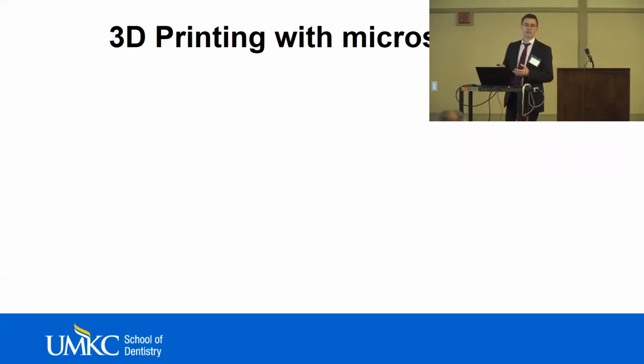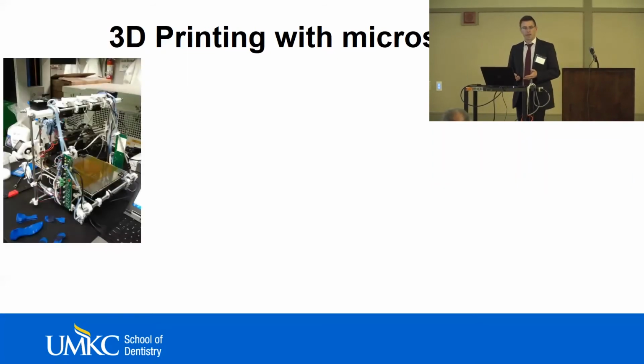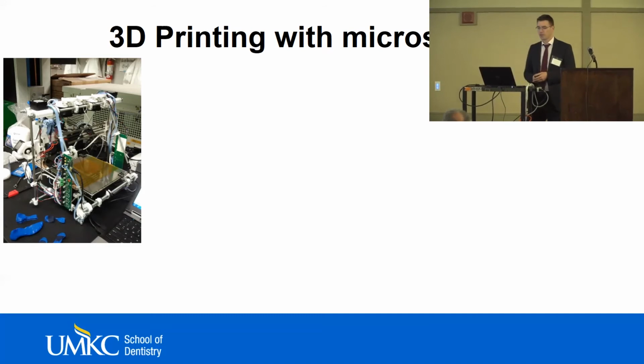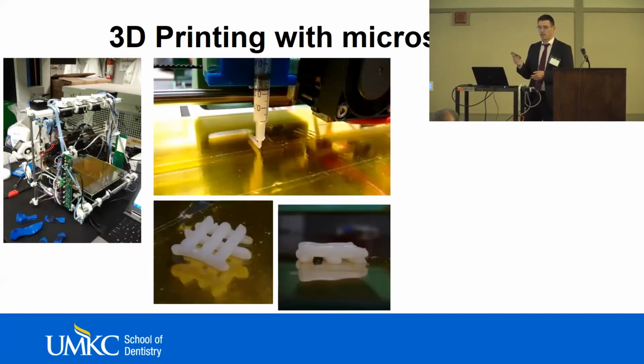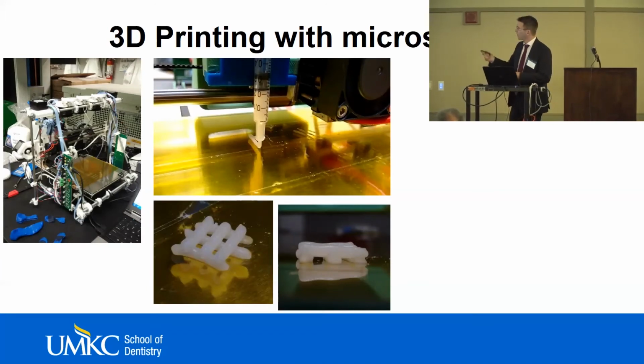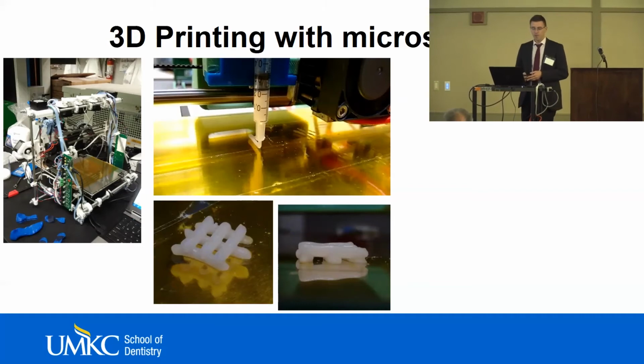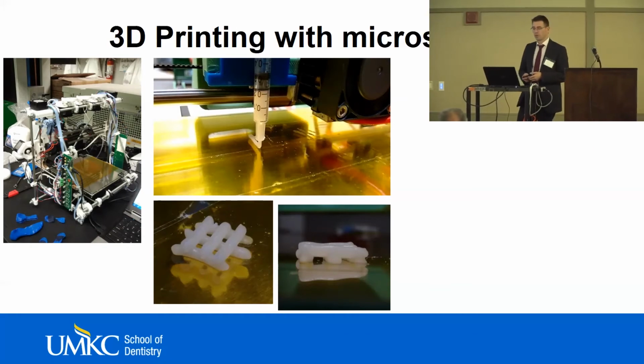So the idea was to combine 3D printing with the microspheres. And to be able to print the microspheres, I had to use a binder, a matrix material, to keep the microspheres in shape until they're fully sintered and stick together. So I started off with a very simple, homemade 3D printing process and a small range of different matrix materials. And with them, I was actually able to create strands of microspheres that could be extruded from a syringe and that stayed in shape until sintered, thanks to the high viscosity that I chose for my binder. Now, with this system, I couldn't create very high pressures, so I couldn't go down to very small diameters.